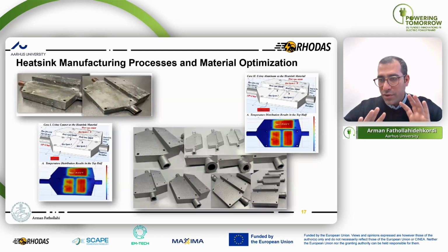We built and manufactured these two heatsinks first in copper, because copper has better characteristics for thermal and heat dissipation. But unfortunately, because of the holes, we couldn't come up with a good 3D printing procedure without any leaking, because leaking could be a very big problem when you have a DC link voltage of 1000 volt.